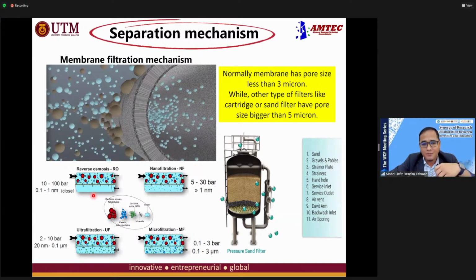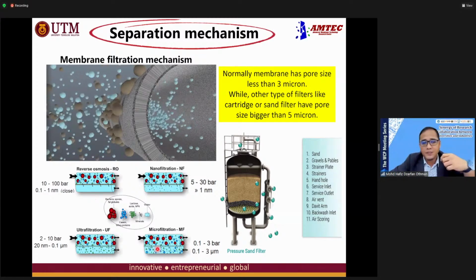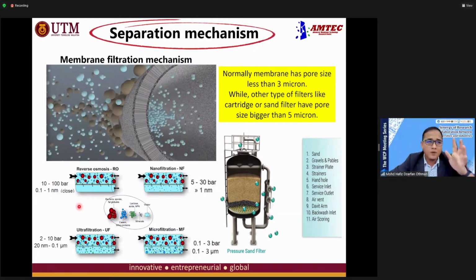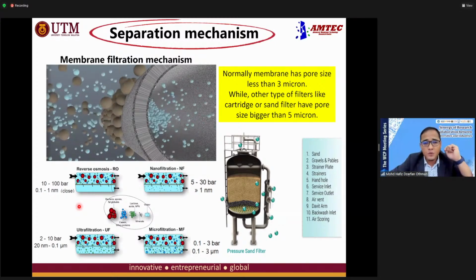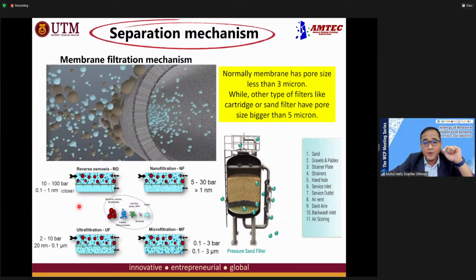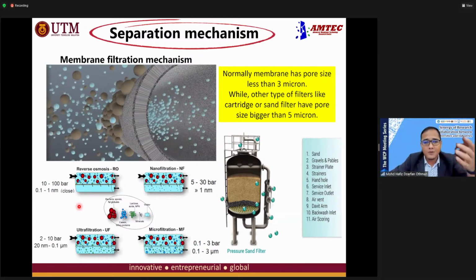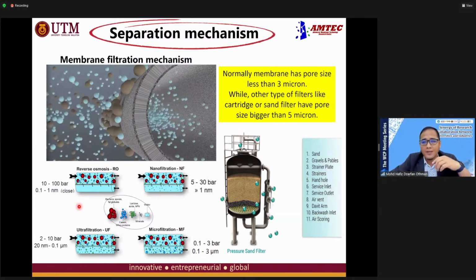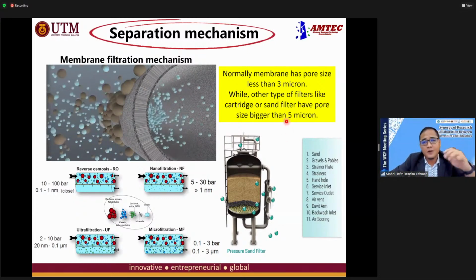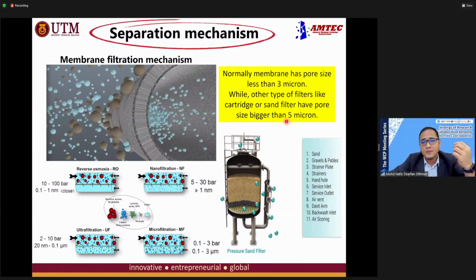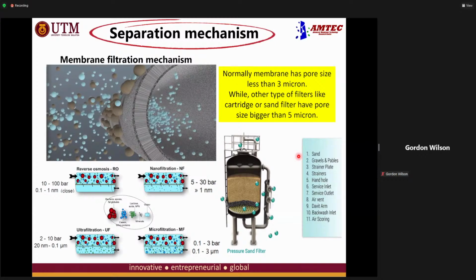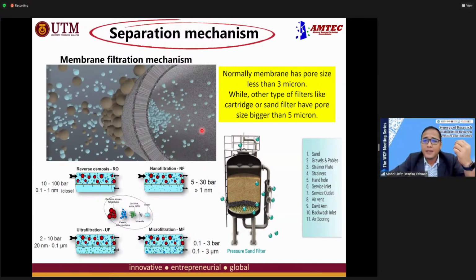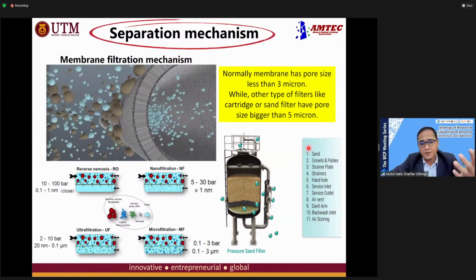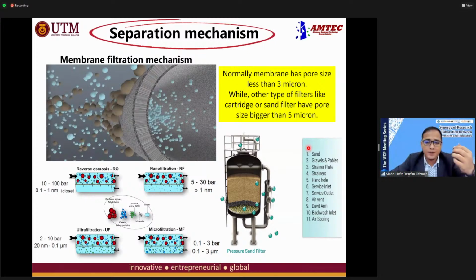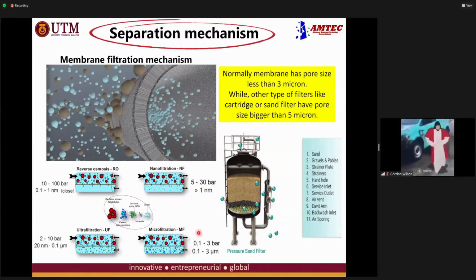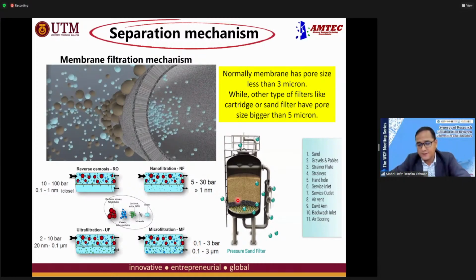The smaller the pore size of the membrane, the higher the operating pressure that needs to be used, because the pore is too small, so the resistance is very high. So we need to push using high pressure in order to allow only some constituents to pass through. Maybe people also wonder what is the difference between a membrane and other filtration processes, for example, cartridge or sand filters. These types of cartridge and sand filters have the same mechanism as the membrane, but their pore size is normally bigger than 5 micron. On the other hand, membranes like microfiltration have a pore size of less than 3 micron. So that is slightly the difference between them.